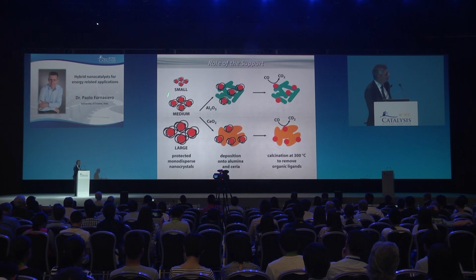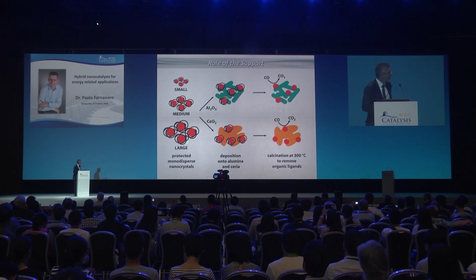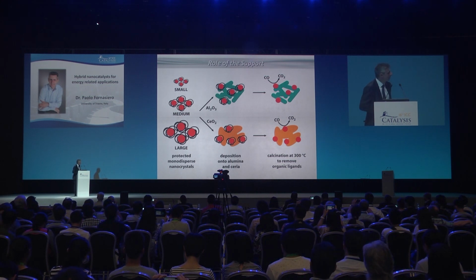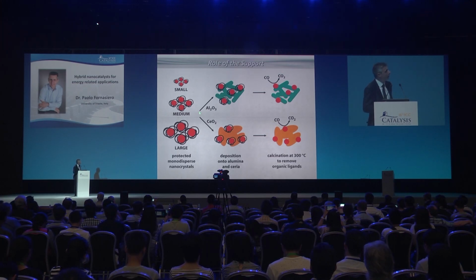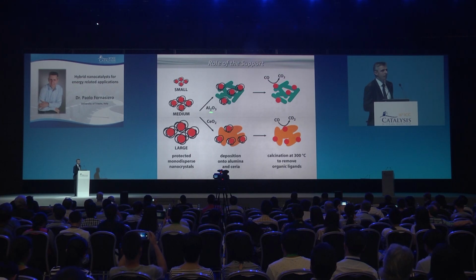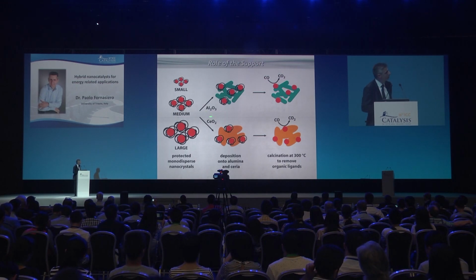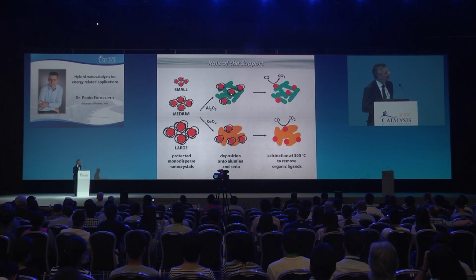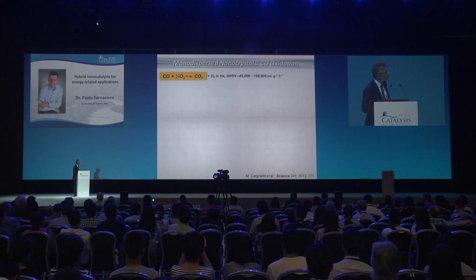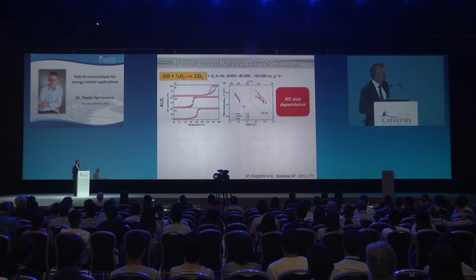And then having this library of protected nanocrystals, we decided to deposit on two types of supports: an inert support like alumina, and a reactive redox support like cerium dioxide. And after gently removing the capping agent, we test this catalyst for the CO to CO2 reaction. And the results are reported here.